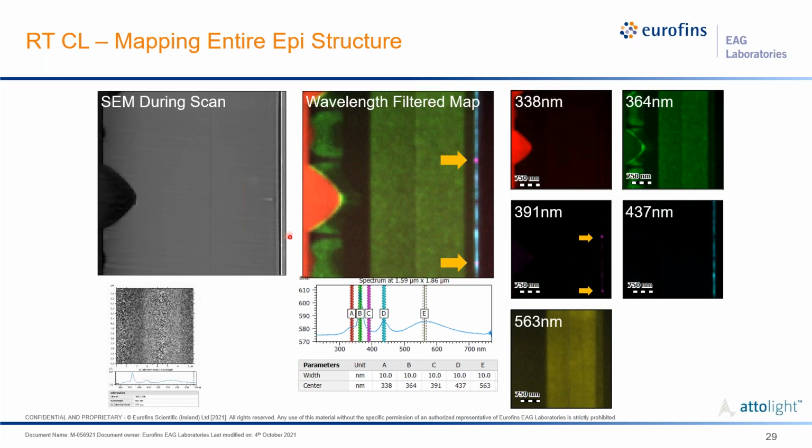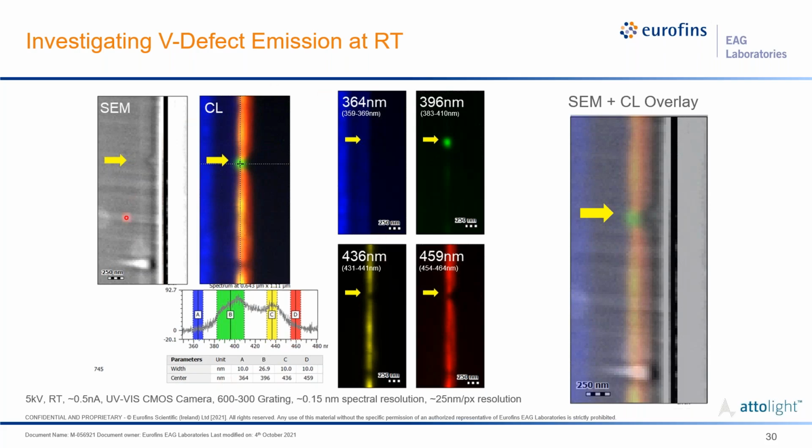We can also visualize very quickly the different materials that are present in the sample, and the variety of different aspects of the luminescence in the growth, right? This first GaN buffer layer has some very interesting geometries to it. Then we see this elevated, increased emission in these second and third layers as well. For some reason, the emission in these layers is being suppressed. Similarly up here.